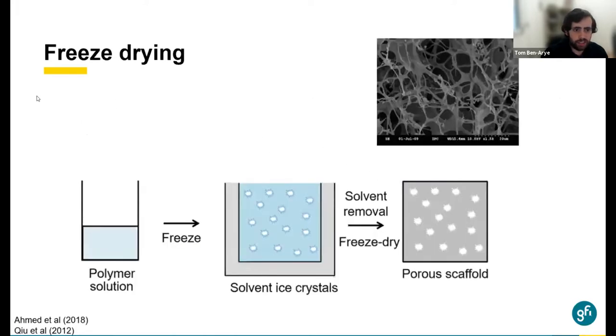Another technique is freeze drying. This is for hydrophilic scaffolds. You take a polymer solution and you freeze it slowly. And while the solvent slowly generates the ice crystals, the polymer is deposited between the crystals. And if we then remove the ice crystals by sublimation, we will get an image like the one that you see here on the right: a connected polymer formed around the ice crystals. And this is an example of how you can create a scaffold from a polymer.